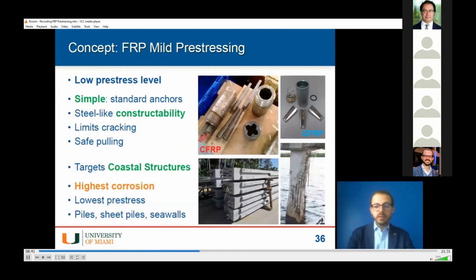If you think about it, you can mitigate all of these issues by reducing the level of pre-stress that you apply to your strands. If you reduce the level of pre-stress, you can use simpler anchors, smaller anchors, and you can still achieve high constructability. You can limit cracking in your concrete because that is directly proportional to the level of pre-stress that you apply. And you can also achieve safer pulling because now you're working at a level of pre-stress that does not represent a hazard for people working outside.